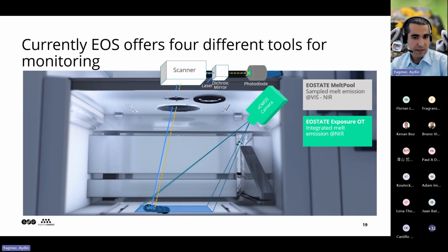The second system is a camera, so it knows where the signal is coming from. No additional information is needed for the data, and it takes pictures during the layer time. So it takes pictures before, during, and after melting, and we can have an integrated image of the full build plate. A big difference between OT and melt pool is that with melt pool, we can gather data only from where the laser is melting. So we cannot get data out of the parts that are being fabricated. But with OT, we can also get data from the surroundings, so the whole build plate.